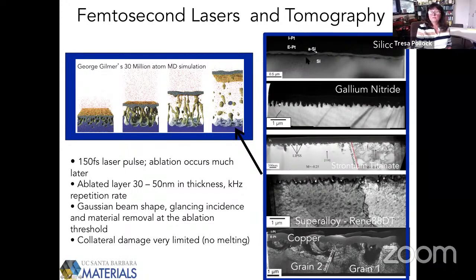And what we're showing here is the fact that you can ablate material with very little collateral damage to the material, with the possible exception of very, very soft materials, because when you ablate, you launch a shock wave here. And so in very soft materials like copper, you do inject some dislocations into the surface. There's also a little bit of roughness, and this has to do with the details of the laser material interaction, but these things do not interfere with imaging. The other thing you'll notice is that a lot of different materials can be ablated without any substantial damage.